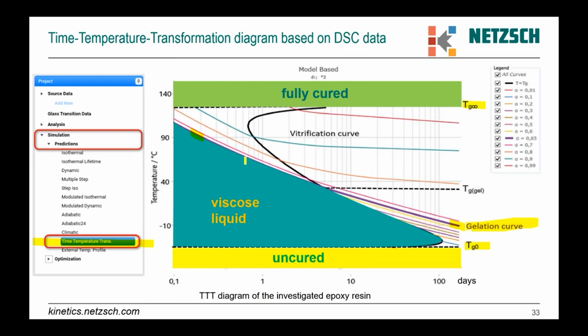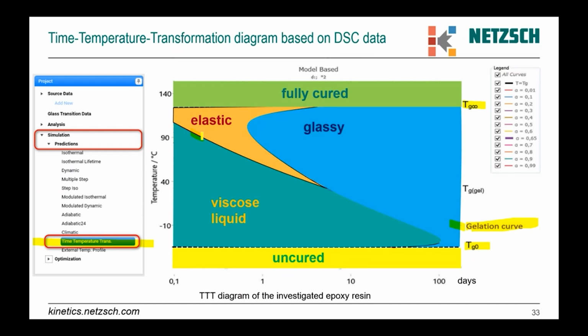Here, from the beginning up to the gelation curve, we have a viscous liquid. Between the gelation curve and the vitrification curve, we have an elastic state of material. And after vitrification, we are below glass transition and we have a glassy state. With this diagram, we can read what time is necessary for isothermal conditions to reach the gelation curve and the vitrification curve. For example, for a given isothermal temperature for many days, we can find at which time we have gelation, changing from viscous liquid to elastic, and at which time we have a change from elastic to glassy state.